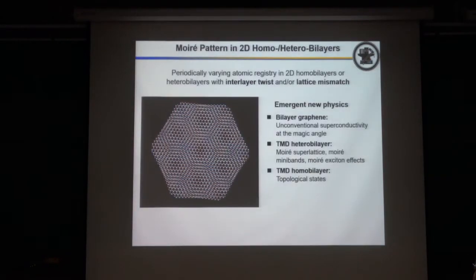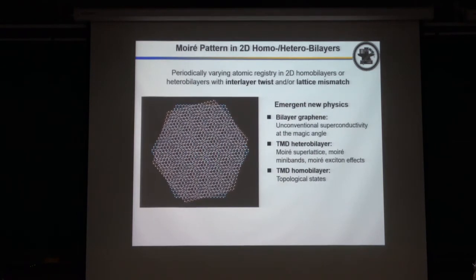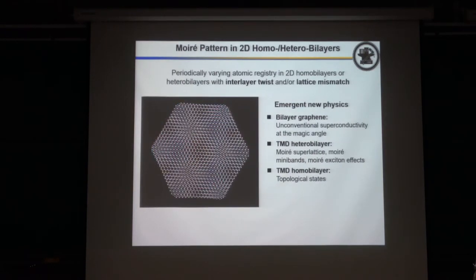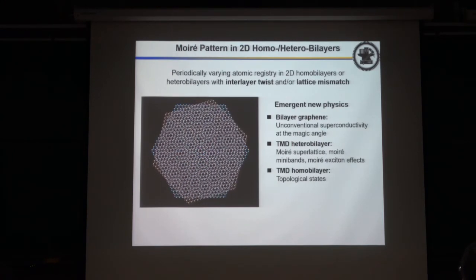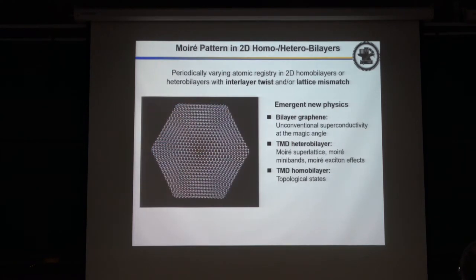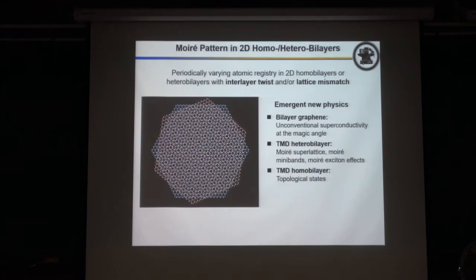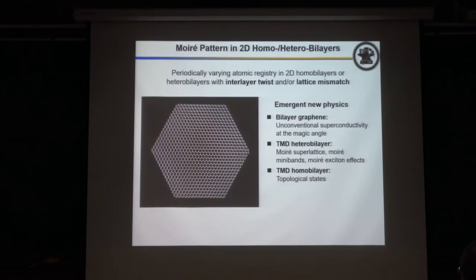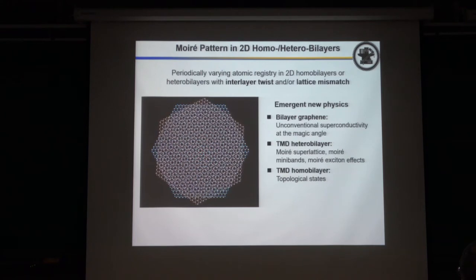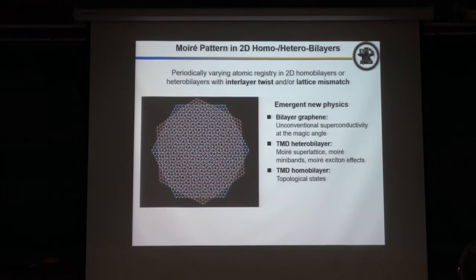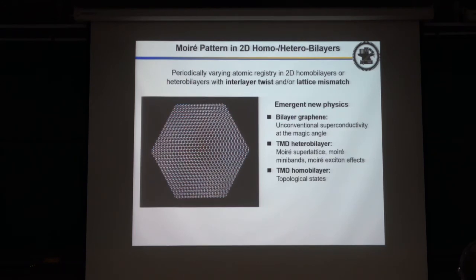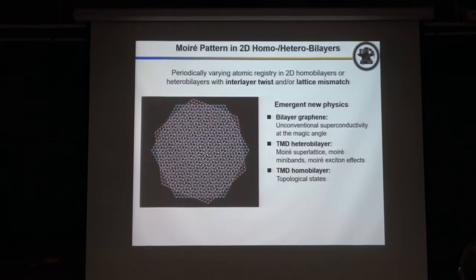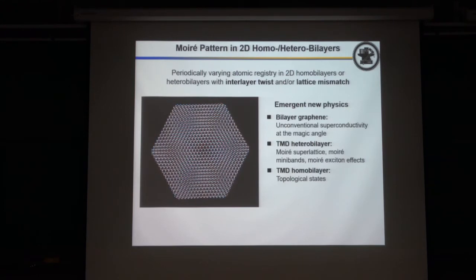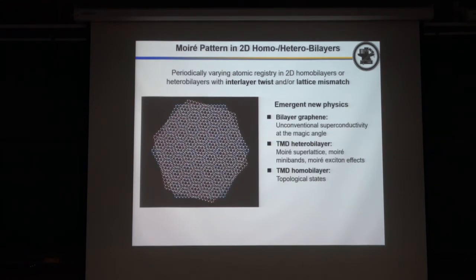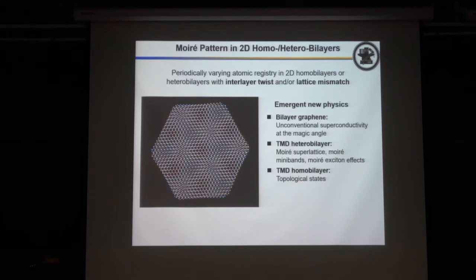And this is, I just introduced some commensurate case, but for the case with the Moiré pattern, the periodicity will change with the twist angle. So in the past few years, people tried to study this kind of bilayer system with Moiré pattern, and found very many interesting phenomena, like unconventional superconductivity in bilayer graphene. This is very famous in the past 2 years.